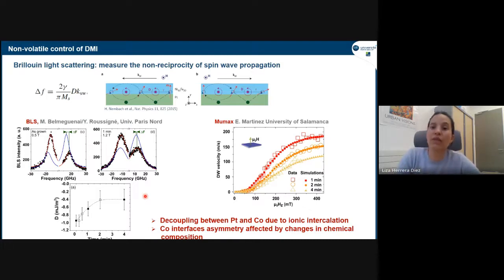However, we cannot forget that, for example, in charge-based devices, there still is a change in the DMI that is induced by only playing with the top interface. We know that the DMI comes from the asymmetry between the two interfaces. So we know very well that we are also changing very much the top interface. This will definitely contribute to the final result and to the complexity of the system. But we do have evidence that there is a change also in the bottom interface.